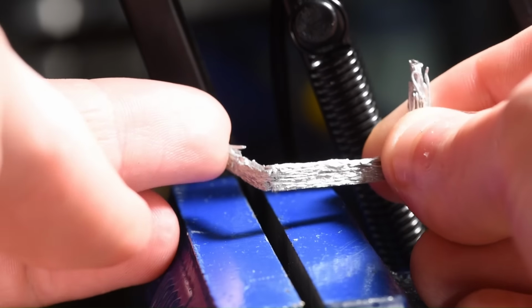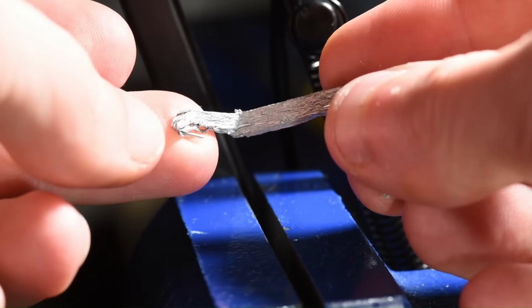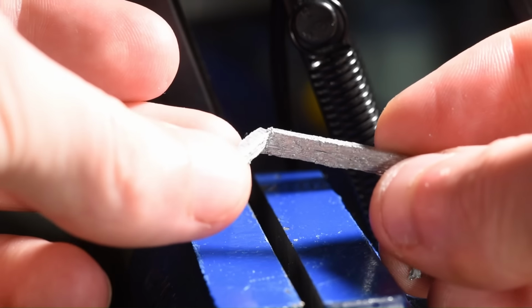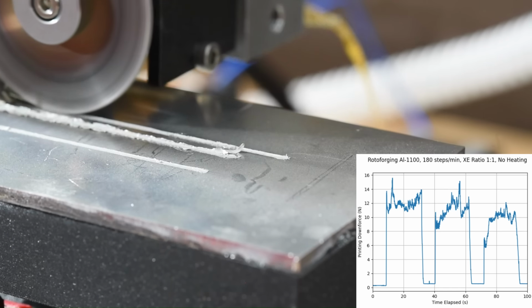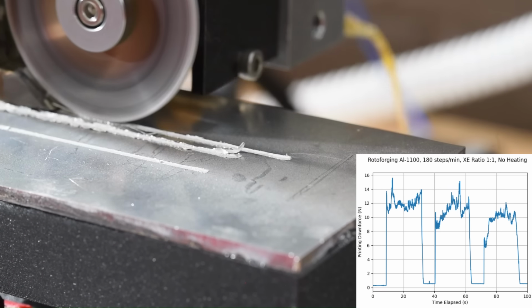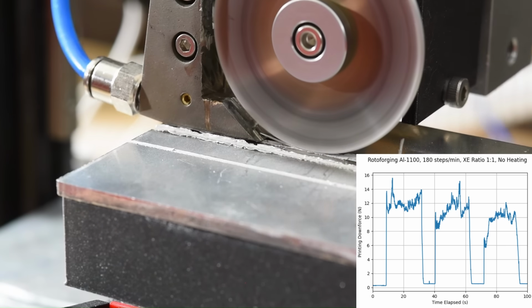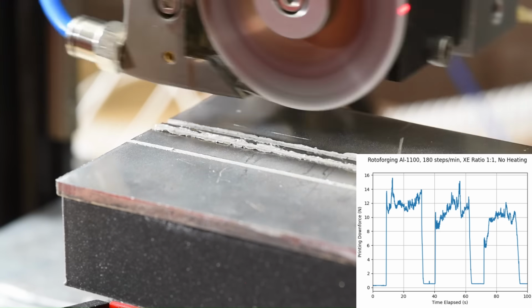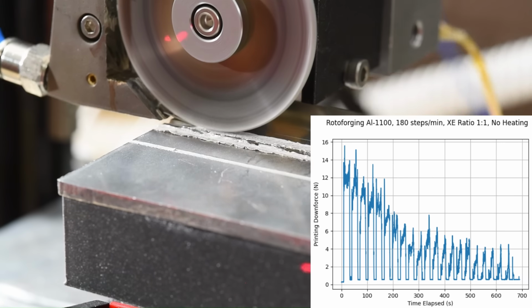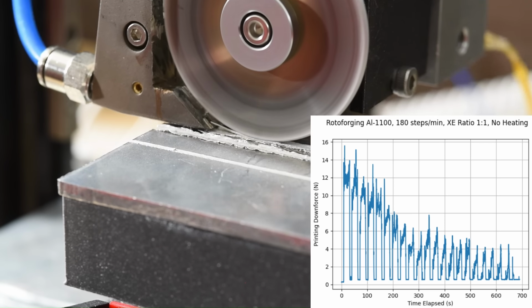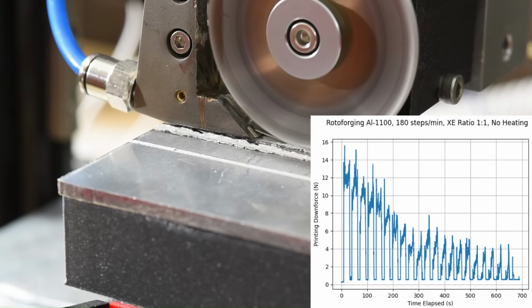Of course, now that we collected this basic bit of quote-unquote mechanical testing, we became curious about deposition forces and eventually deposition temperatures. So Sam courteously set up a scale, a load cell on which we could print with a piece of aluminum stuck on top of a PLA printed block, and we started collecting deposition force data. Startup forces, when you dive far too deep into the aluminum plate before you start actually feeding wire, are in the tens of newtons, but quickly fall to single digits, 3 to 5 newtons of downforce as the process becomes more stable and you reach something that looks a bit more like steady-state deposition.